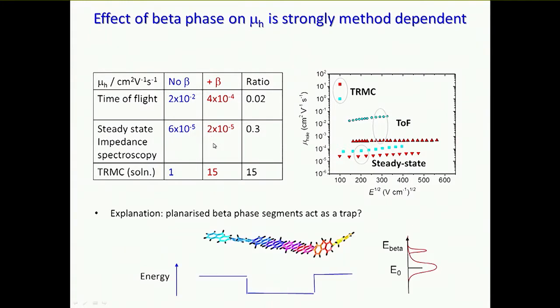So the obvious thing is to think about what this planarized phase is doing to the energy of the electronic states. And what it does is it's going to present an interval where, because of the strong conjugation between successive monomers, you have some stabilization of the hole. So the hole is going to prefer to lie in this planarized segment than in the non-planar ground state segments that would be attached to it on either side. And so this planarized segment we could effectively expect to act like a trap.